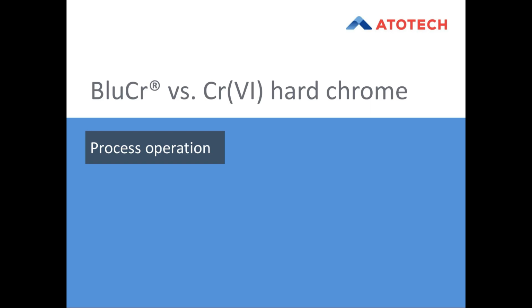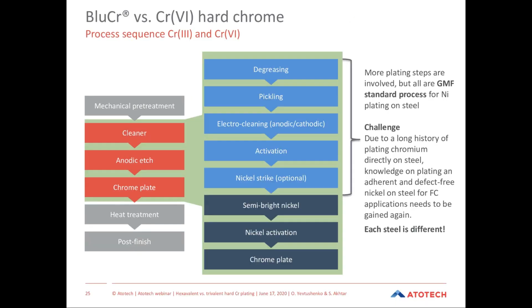Now coming to the next point, process operation. Here on this slide, on the left side is the process sequence for usual plating of chromium from a hexavalent bath, and on the right side the same for blue chromium. You can see that the mechanical pre-treatment and post-treatment remain the same for both. But in the case of hexavalent chromium, first the parts will be cleaned, then may be subject to anodic etch, and then later the parts go in for chromium plating.